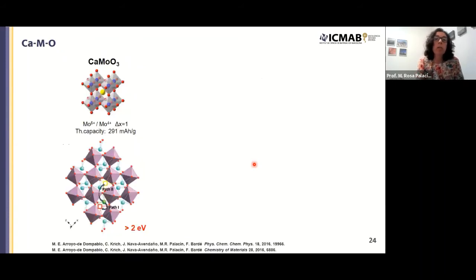In our case, we naively focused at the beginning on perovskites, because as you know, this is a very rich family of calcium transition metal oxides. We collaborated with Elena Arroyo at Universidad Complutense de Madrid to do some DFT calculations, and it turned out that the molybdenum perovskite would be very interesting in terms of potential. We were able to prepare it, but when we tried to extract calcium electrochemically, it was not possible. We understood why when she calculated the migration barriers for calcium in the structure, which are rather high.